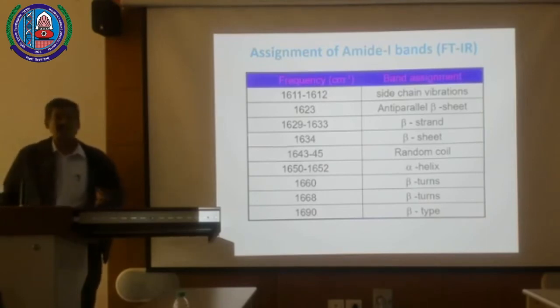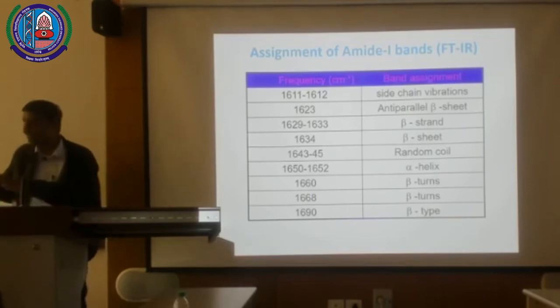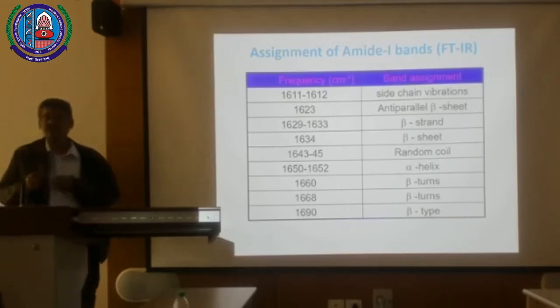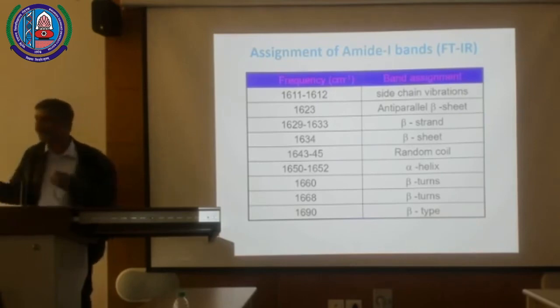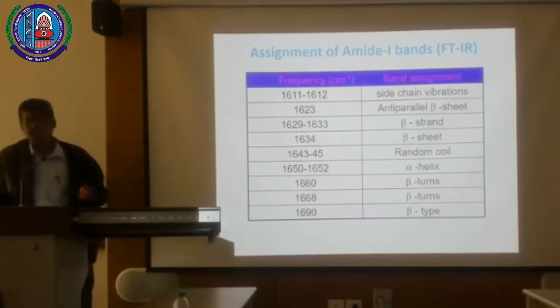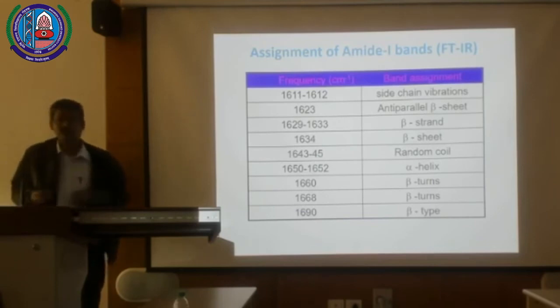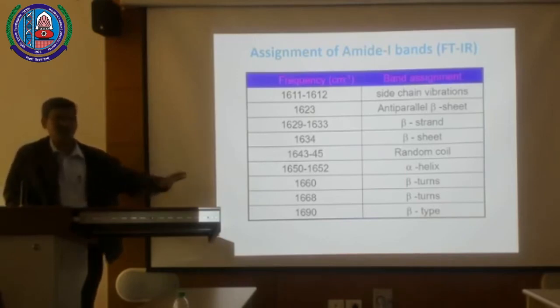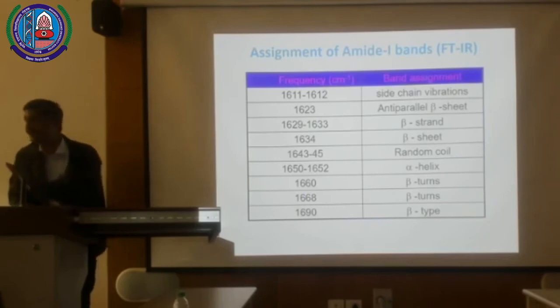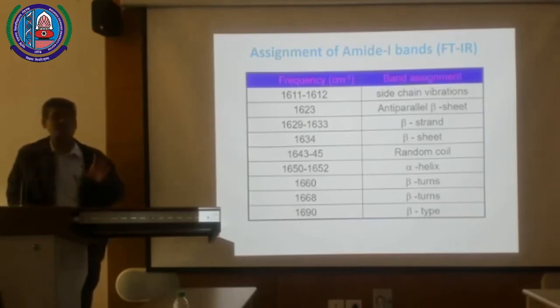A simple way is to take a denatured protein, you just heat denature it. You know its denaturation temperature. Any protein you take, put at 100 degrees for 10 minutes and the protein is denatured. Maybe whey protein, I'm talking about a minimum of 10 minutes. Then you take a native protein and study it under the FTIR spectra. Then you will definitely see how the peak shift is occurring. This is experimental detail, you can quickly do it yourself.